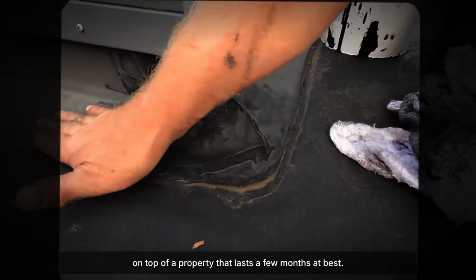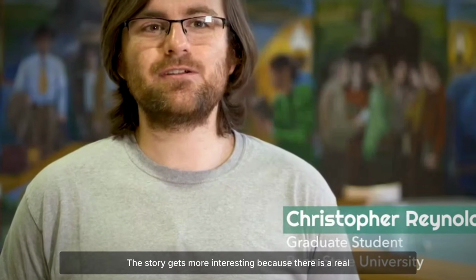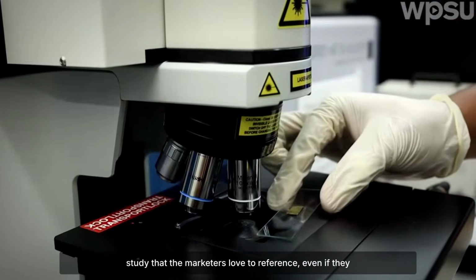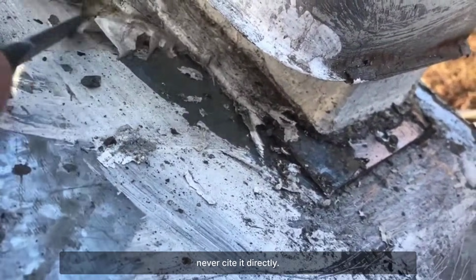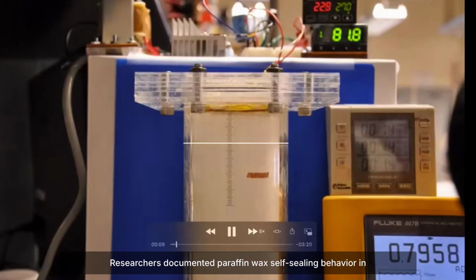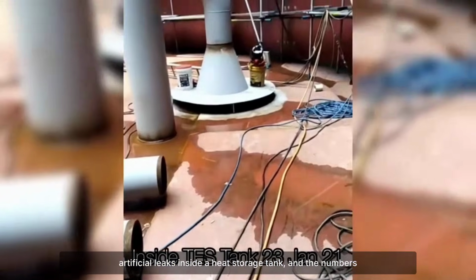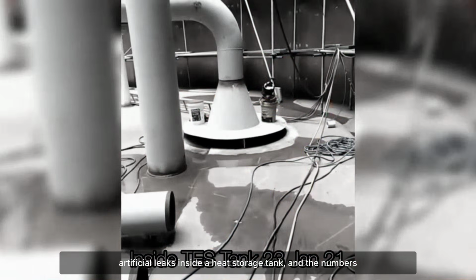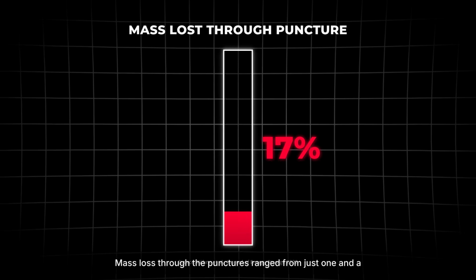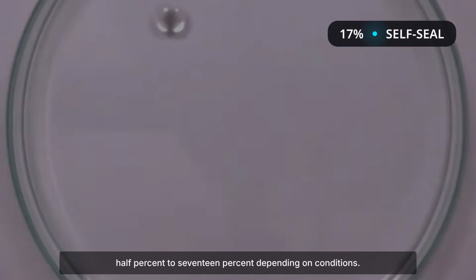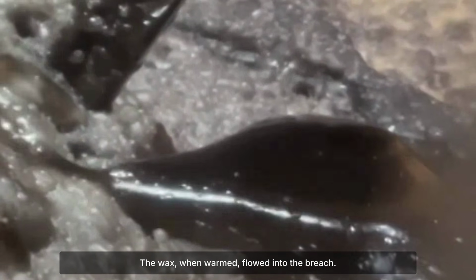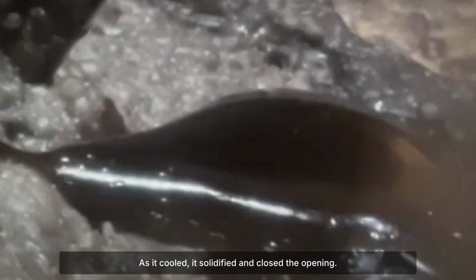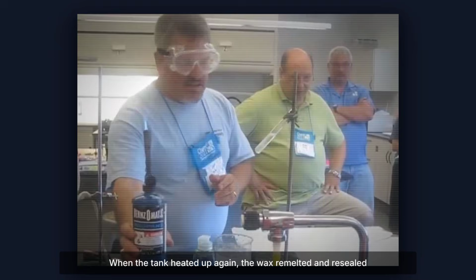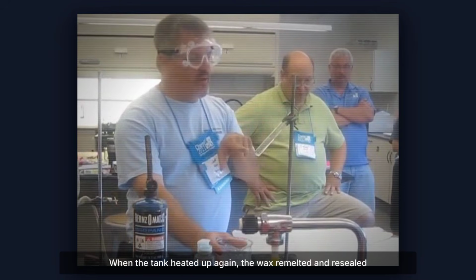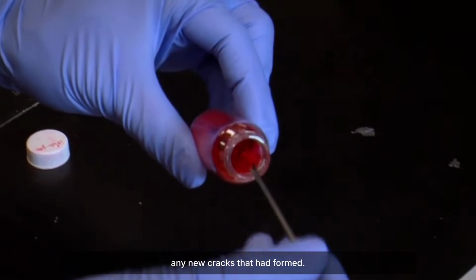The story gets more interesting because there is a real study that the marketers love to reference, even if they never cite it directly. Researchers documented paraffin wax self-sealing behavior in artificial leaks inside a heat storage tank, and the numbers are striking. Mass loss through the punctures ranged from just 1.5% to 17%, depending on conditions. The wax, when warmed, flowed into the breach. As it cooled, it solidified and closed the opening. When the tank heated up again, the wax remelted and resealed any new cracks that had formed.